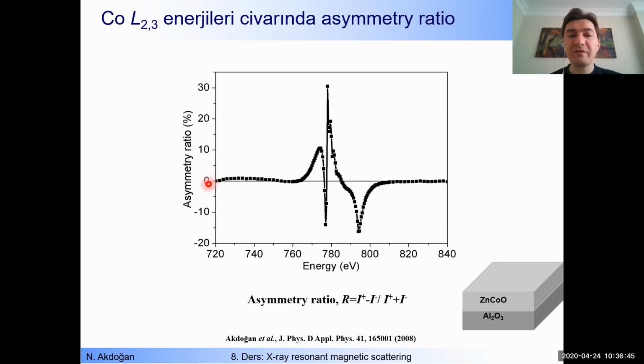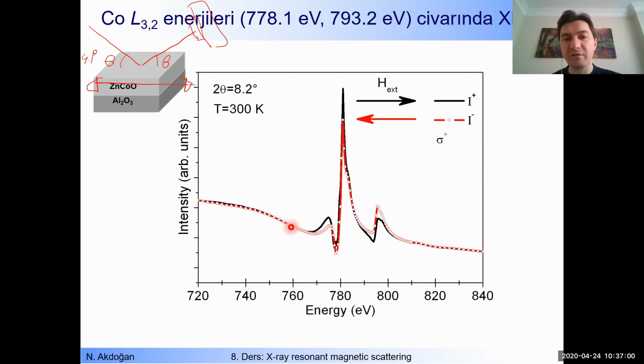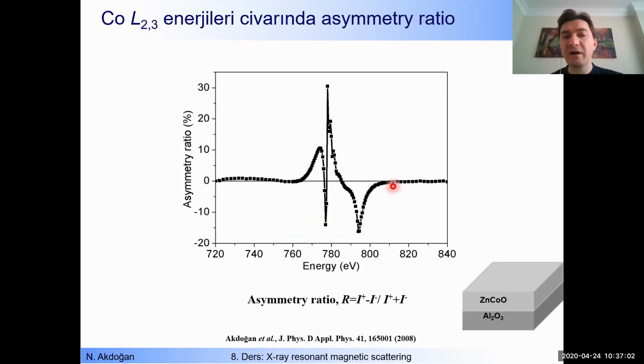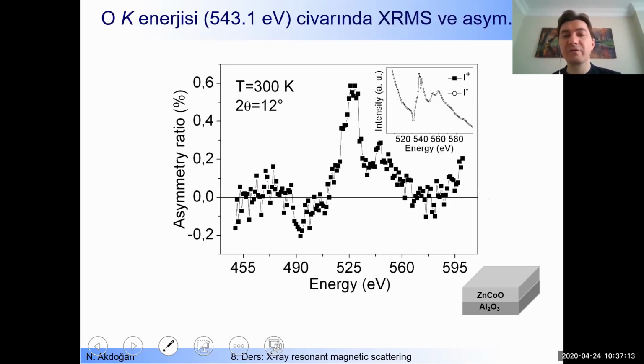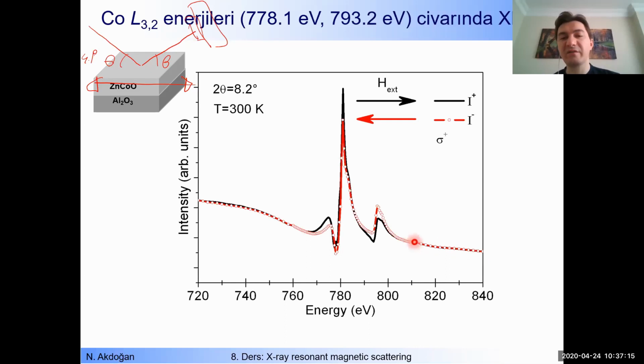So what do you see here? Until we are coming to the cobalt L2, L3 energies, we see more or less no difference. Actually, there is no difference here. And also after passing the L2, L3 energies, again, we have more or less no difference. Asymmetry ratio oscillates around 0, okay? So you can also see it here. There is no difference here.